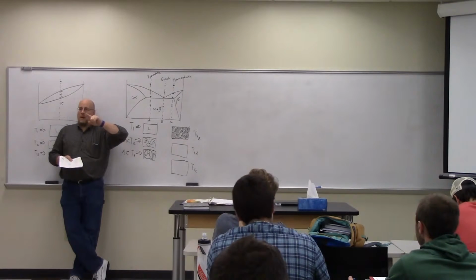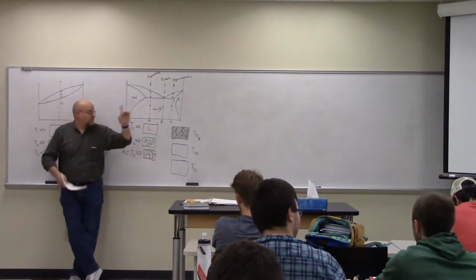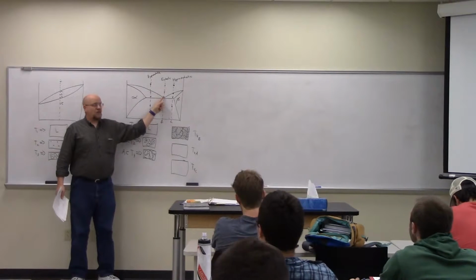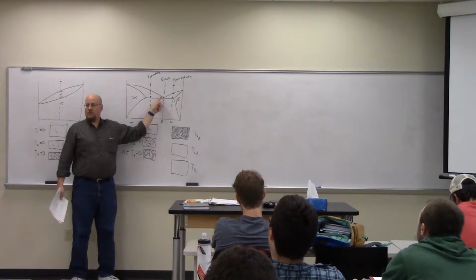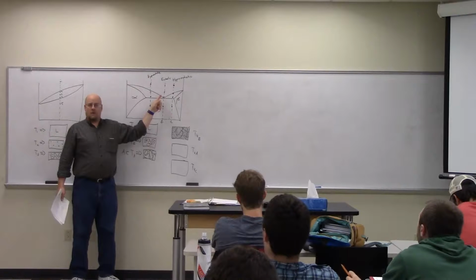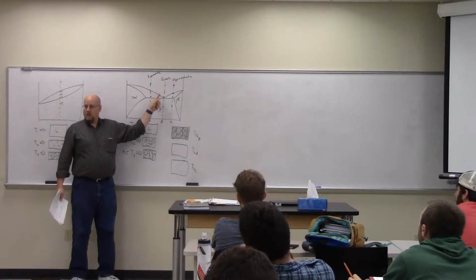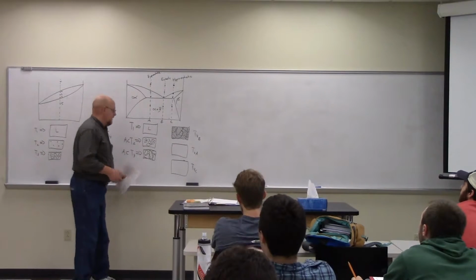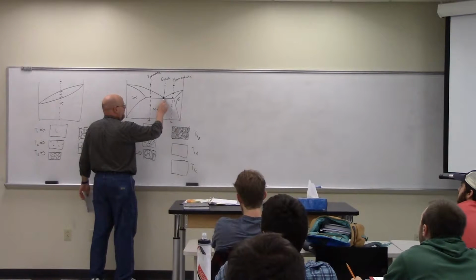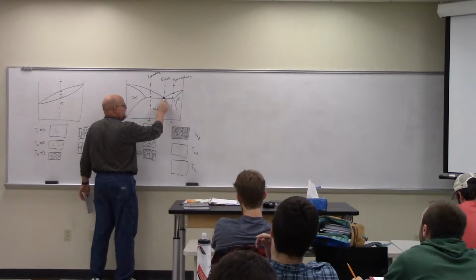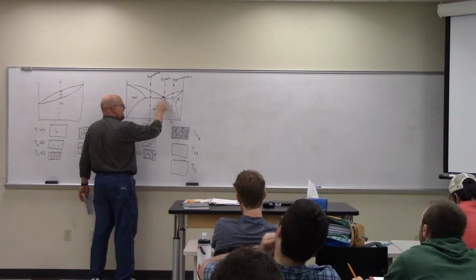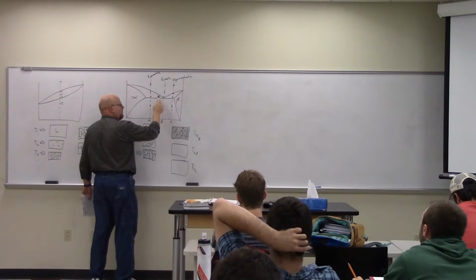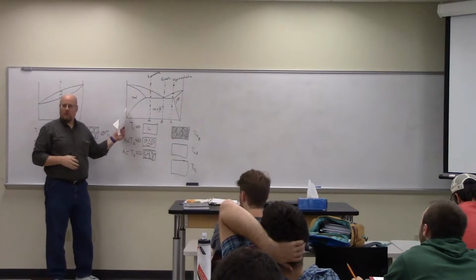But then suddenly I've shifted. If I pull out a little beta, then I shift my concentration over here to the left with my liquid. You see what I'm saying? Never had an actual eutectic. So as soon as I pull out a little bit of tin, the rest of the liquid that hasn't solidified yet shifts over and is alpha, or lead-rich.